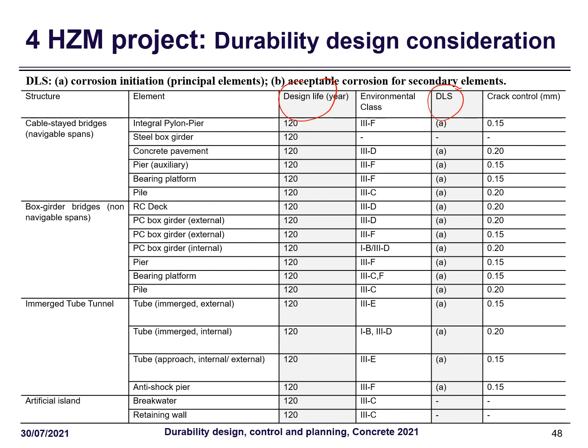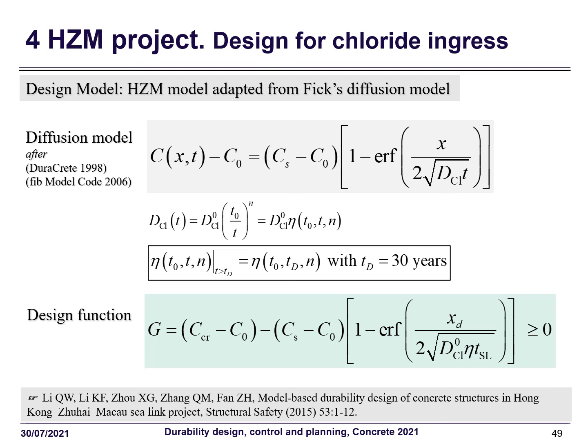life, the DLS, and here are the choice of design service life and the DLS for the main concrete elements in question. And for chloride ingress, we use model-based design. The model is like the model in DuraCrete. It's a diffusion process, Fick's second law, with an aging diffusivity, and that is the design function. But to apply this equation model to the Hong Kong-Zhuhai-Macau Bridge, we have two problems to overcome.